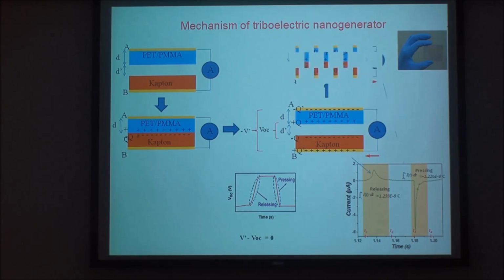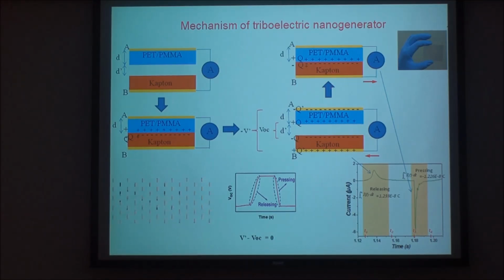Once you release it, it folds over, the gap disappears, the potential disappears, and electrons flow back. The integrated areas are the same because the total charge that flows in equals the charge that flows back. The key is to find a process to make this separation, typically about 10 to 50 micron distance. So you have surface engineering, and this happens automatically when you do the mechanical separation. Okay, so that's the idea for this principle.